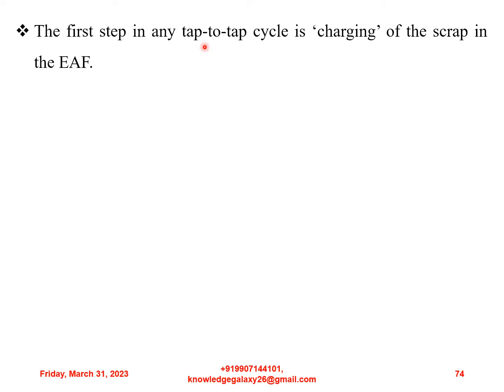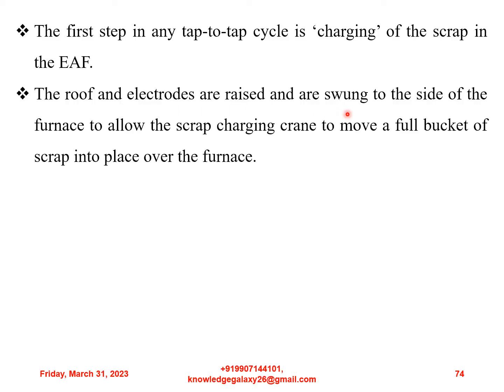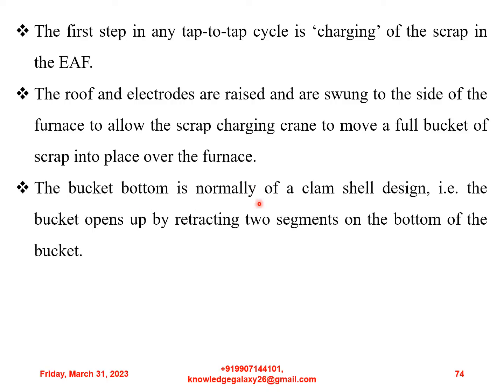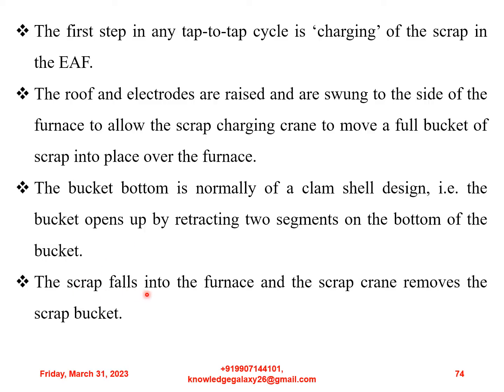The first step in any tap-to-tap cycle is charging of the scrap in the electric arc furnace. The roof and electrodes are raised and are swung to the side of the furnace to allow the scrap charging crane to move a full bucket of scrap into place over the furnace. The bucket bottom is normally of a clam shell design, that is, the bucket opens up by retracting two segments on the bottom of the bucket. The scrap falls into the furnace and the scrap crane removes the scrap bucket.